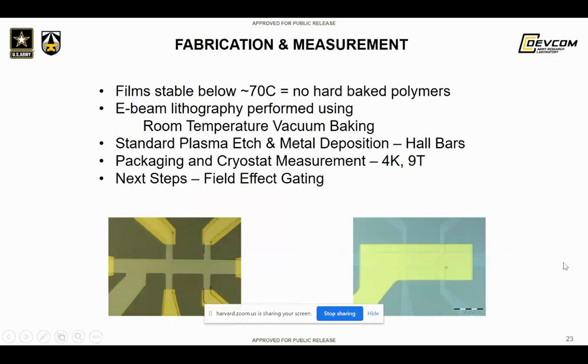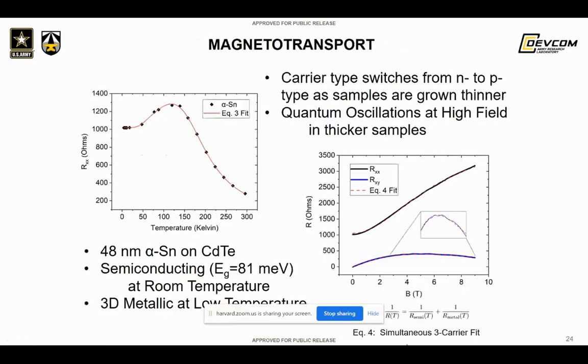We can do fabrication of Hall bar devices. It's not easy, but it can be done, and we can go on and do transport measurements, which was done in this sample. Here are some transport measurements that were done, as we measure, for instance, resistance as a function of temperature. And the data shows, interestingly, some behavior which is metallic-like at low temperatures. And we even saw some small quantum oscillations at high field in this material.